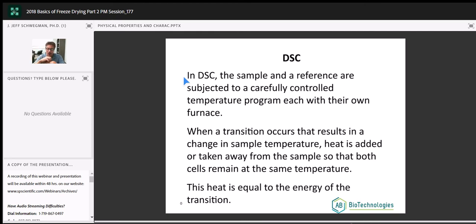So we get the DSC, the gold standard. In this particular case, it's the same deal. We have a sample of our sample, so it's formulated exactly as if we were going to freeze dry it in a vial or a tray. And then the reference is just an empty sample pan. These are little aluminum discs, little aluminum sample pans. The reference pan is empty. We seal it empty. So basically, it's the same deal.